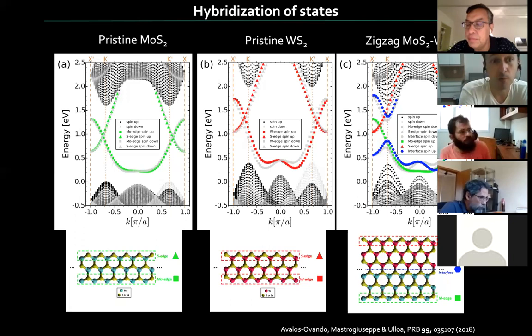But I have to read the paper carefully, because my impression is that if you add a Wilson mass, as I did with Vernac some time ago in a recent paper, if you add a Wilson mass with a quadratic term, you can actually break the crossing at k equals pi, while keeping the physics at k equals zero approximately the same as before. But the trick is that you have to choose the Wilson mass appropriately such that it doesn't break the symmetries of your system. And the idea is that this is always possible.